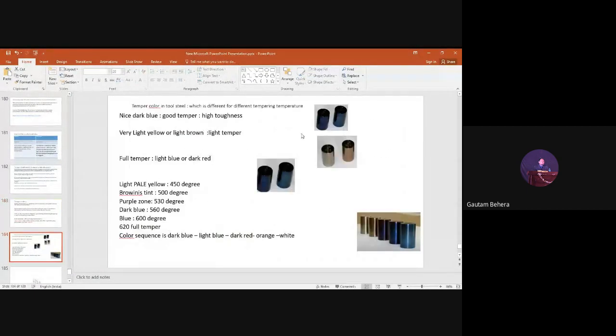I'll show you a very interesting image. You can see these are the different tempered samples: this is the initial temper, this is some intermediate, and this is the final temper. You can do tempering at a high temperature also. These colors are visible when we are tempering tool steels. Tempering of tool steels is obviously essential, because if you do not temper, the tool will break, as the martensite is brittle and has residual stresses. Upon tempering tool steels to get some toughness, you will see different colors: yellow, blue, dark blue, light blue.